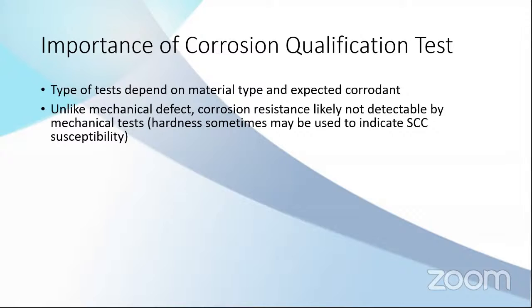Although sometimes hardness can be seen. If it's very hard, then there's a high possibility that it can impact the stress corrosion cracking susceptibility. But for corrosion because of the media, the general corrosion type or localized corrosion type like pitting corrosion, it's impossible to detect from mechanical testing. So you need to add corrosion testing during the PQR.